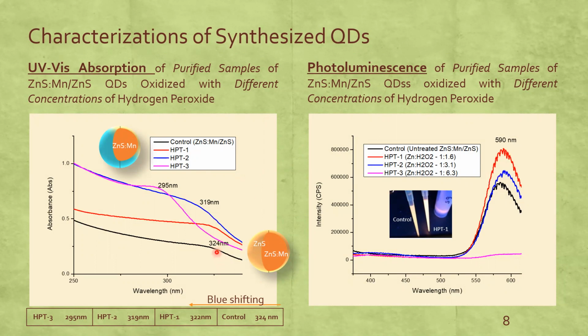Here, the control is observed at 324 nanometer, and we see a consistent decrease in the UV-vis band maxima towards the blue region with increasing peroxide concentration. This means that the band gap is increasing, since zinc oxide has a higher band gap energy than zinc sulfide. This trend indicates that peroxide is treating the surface, is oxidizing the surface.